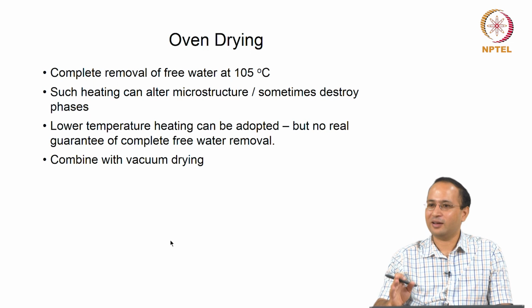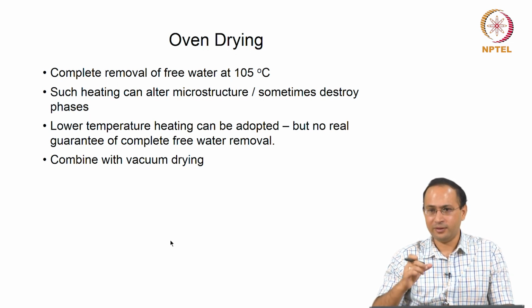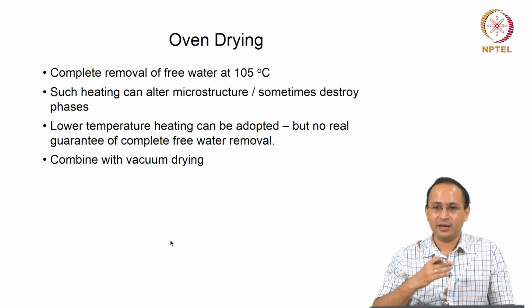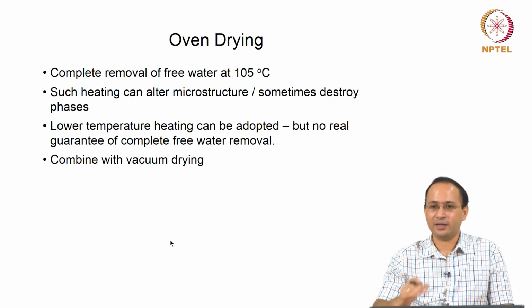But the issue is it is very harsh heating. Such heating can alter the microstructure because you are letting your sample undergo 100 plus degrees Celsius temperature. Sometimes it can even destroy phases, for example Ettringite gets affected if you go above 60-70 degrees, you will start seeing the effect. Even on CSH you will see some effect. So we are talking about 105 degrees Celsius, although you are removing water, you are affecting other phases also. So see the issue.